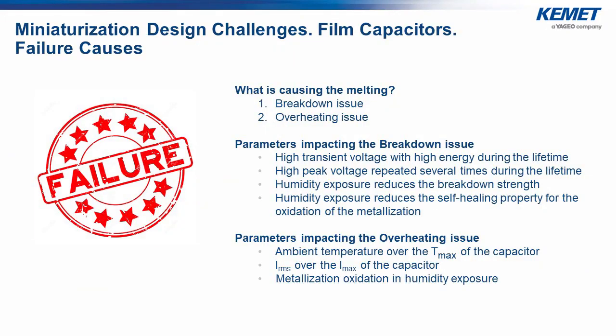So the capacitor can degrade in several ways in a moist environment. There can be different failure causes, like a breakdown or overheating issue, if the capacitor is not designed properly. So which are the parameters that can impact the breakdown? Could be high transient voltage with high energy during the lifetime, or high peak voltage repeated several times during the lifetime. Then also the humidity exposure can reduce the breakdown strength and also the self-healing property of the metallized film, because of the oxidation of the metallization. About overheating, if the ambient temperature of the application is over the maximum declared temperature of the capacitor, it can also cause this overheating issue, and the RMS current, if it is over the maximum declared of the capacitor, can cause the same oxidation of metallization in humidity exposure.